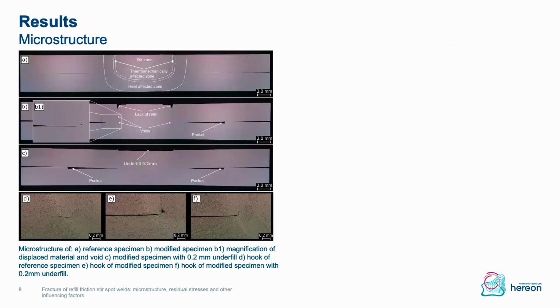This basically results in the microstructure you see on the left-hand side, where we see on top the reference specimen, where we basically have no defects in the weld, and the stir zone, thermomechanically affected zone, and heat affected zone, as mentioned before. Below we see the resulting microstructure from the modified sample, where we see that we have defects, like here we have voids, and also we have a lack of refill.